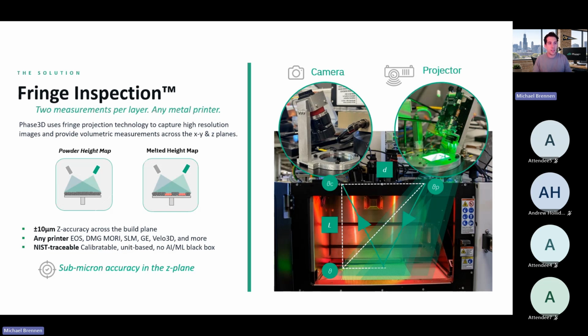We are capturing a minimum of 2 powder height maps per layer, and those powder height maps are captured after recoating and then after exposure. So what we see after recoating is hopefully a perfectly flat surface with just normal variation coming from the distribution of the particle size of the powder and its particle size distribution.